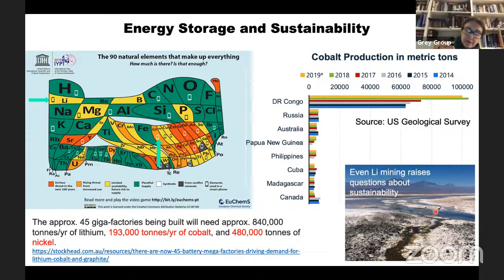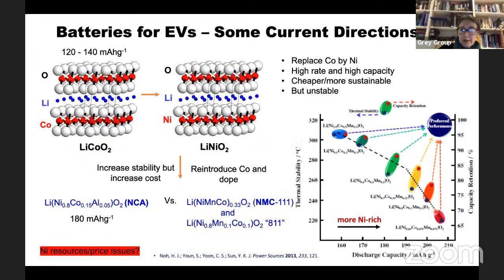So this is just a sort of statement that as we increasingly build more batteries, it has to be done in a sustainable way for us to even imagine how we're going to do this for electric vehicles, let alone for grid storage. So what are some of the current directions? Well, the move from lithium cobalt oxide to lithium nickel oxide was motivated by this cost issue and the mining issues associated with cobalt, but also motivated by higher energy density. So you can get more lithium out than you can in the lithium cobalt oxide in a stable fashion, but it's still not stable enough.